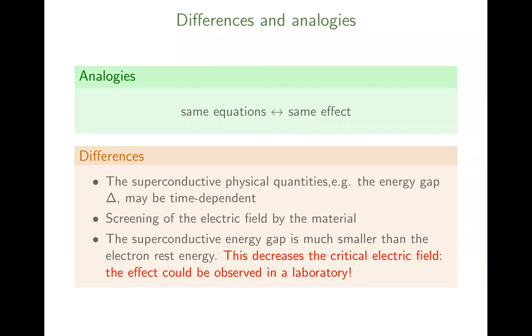One important point is that, contrary to what happens in the vacuum of QED, where you don't have any screening effect due to the lattice or the ions of the material, here the screening effect is typically important. So in principle, it was believed for a while that the electric field wasn't penetrating deep enough in the superconductor to activate any important effects. We will come to this point later. But another important fact, as I told you before, is that the naively computed critical electric field is way lower, and you can actually test your theory in a lab.